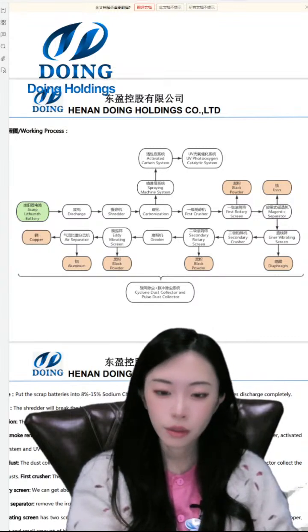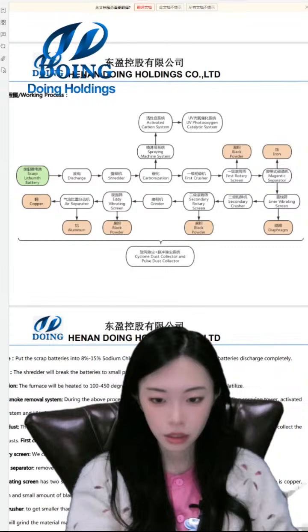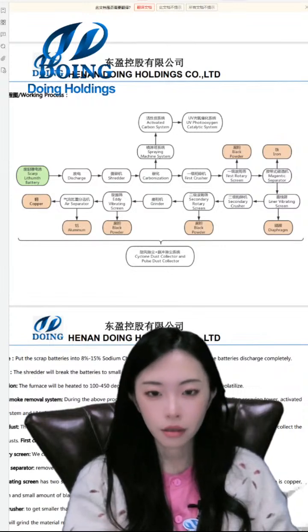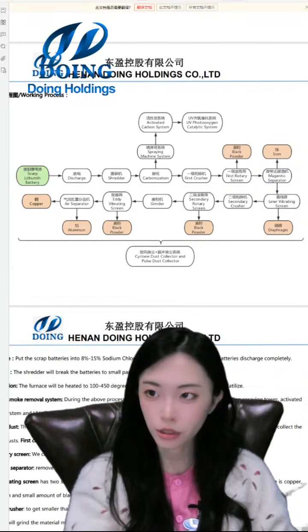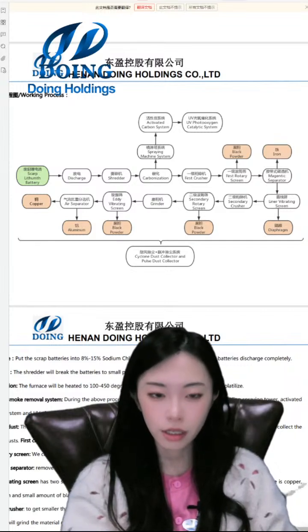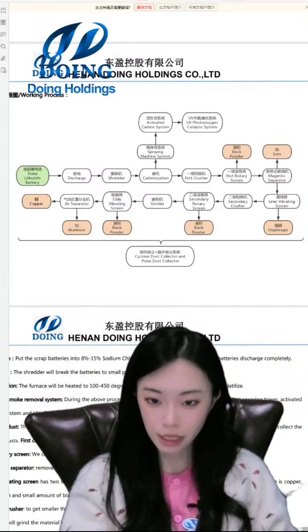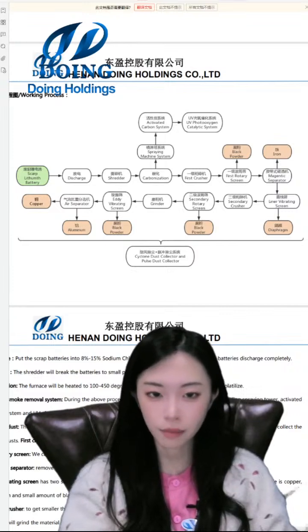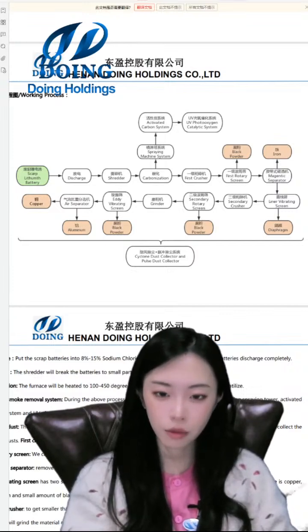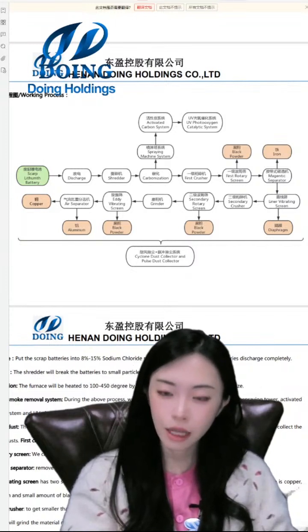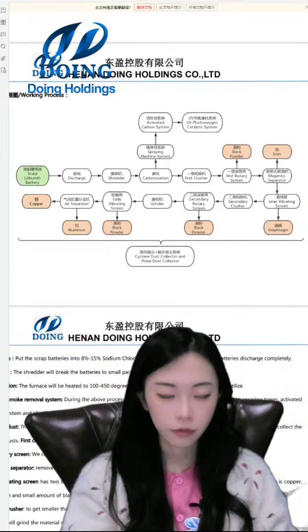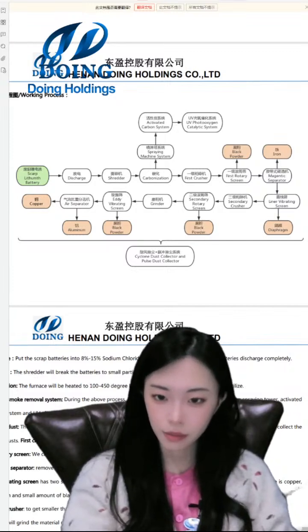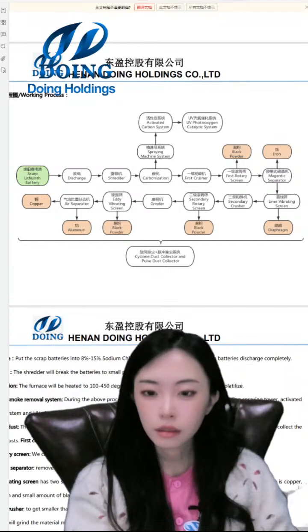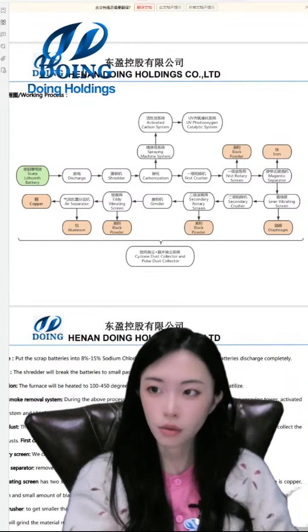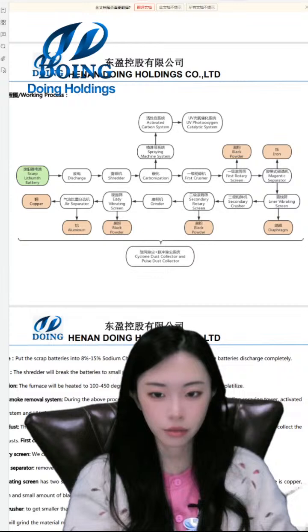First, we will use the crusher. This is the hammer crusher or hammer blade crusher. It's a kind of impact crusher that uses the high-speed rotation of the hammer blades in the crushing chamber to crush the material, and the particles will be crushed to less than 10 millimeters from 3 to 5 centimeters. And then the crushed particles will go into the first rotary screen.